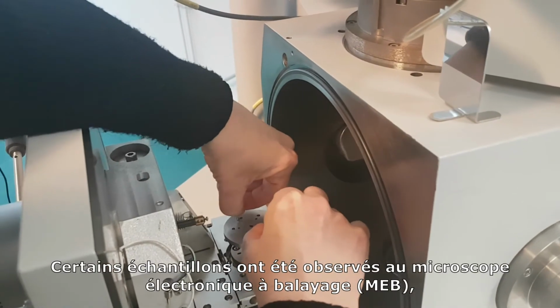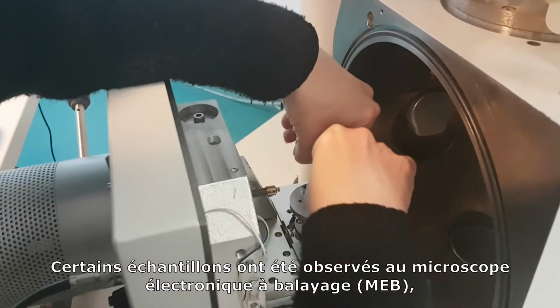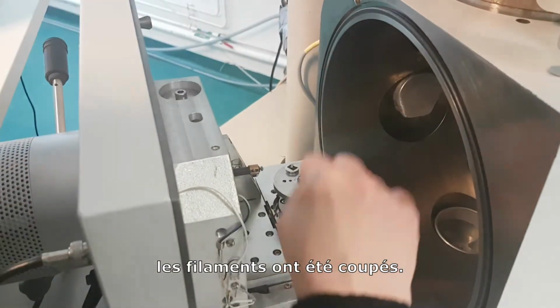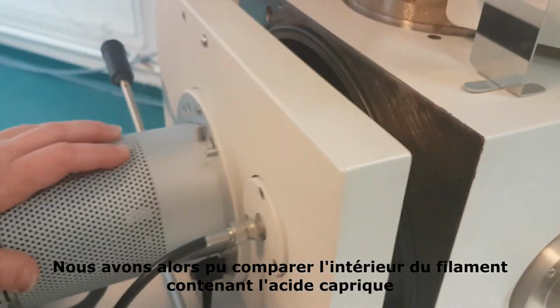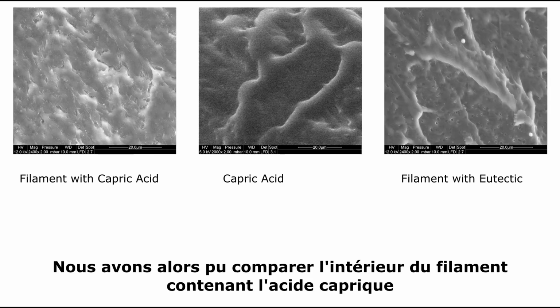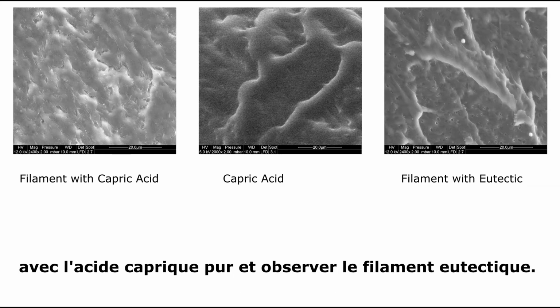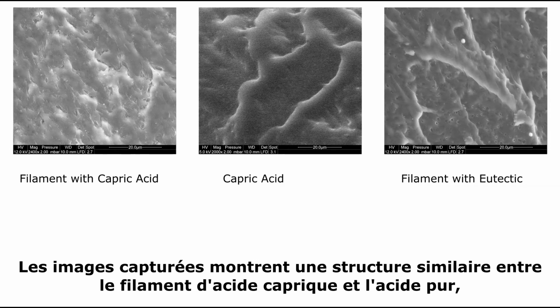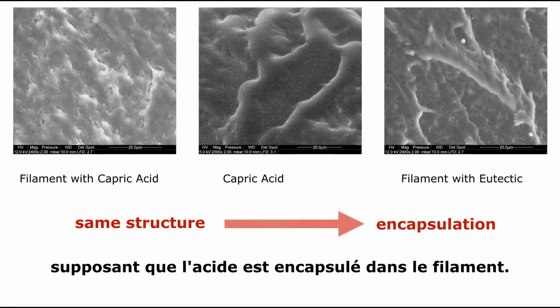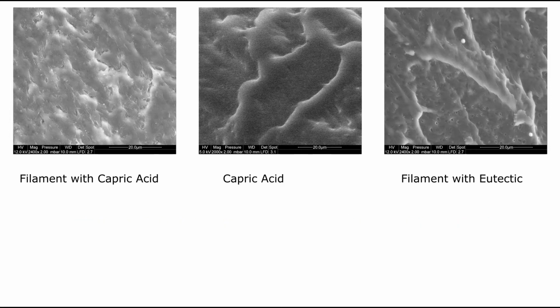Some samples were observed under environmental scanning electron microscopy. The filaments were cross-cut. We could then compare the inside of the filament containing capric acid with the pure capric acid and observe the eutectic filament. The images captured showed the same kind of structure between the capric acid filament and the pure acid, proving that the acid is encapsulated in the filament.